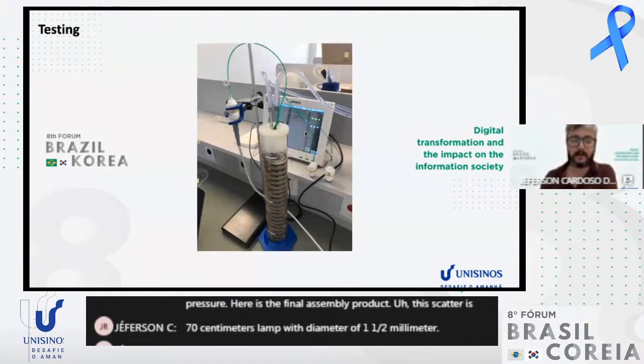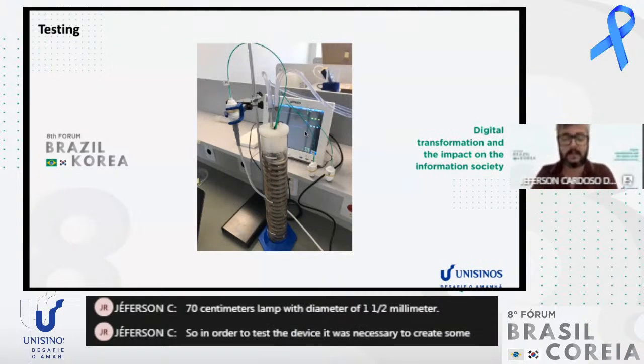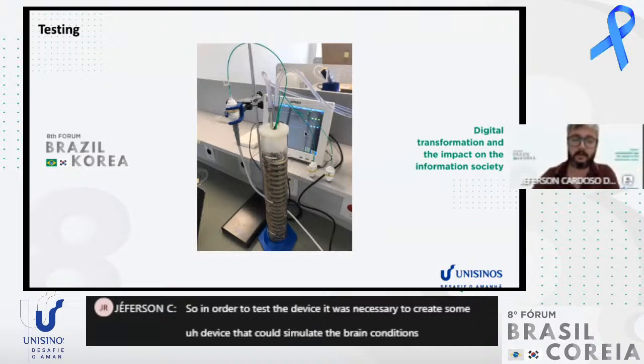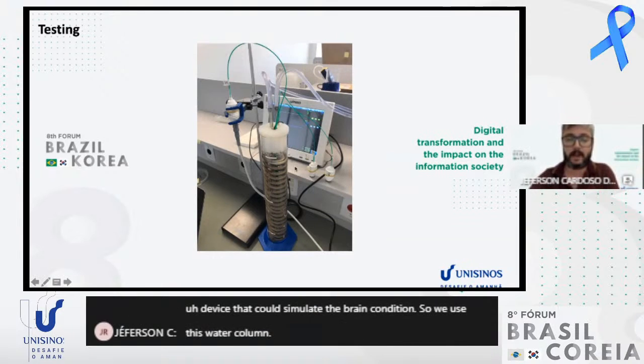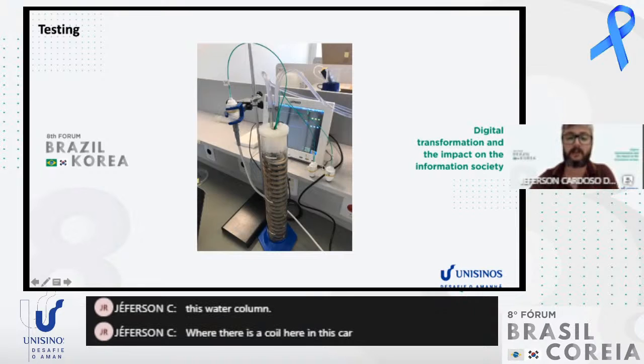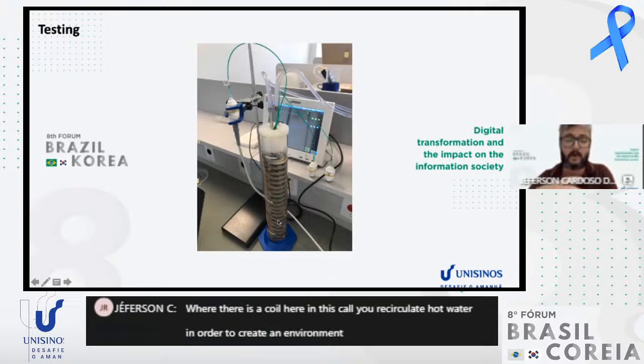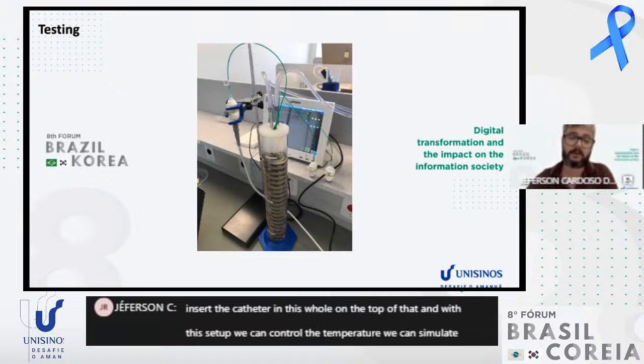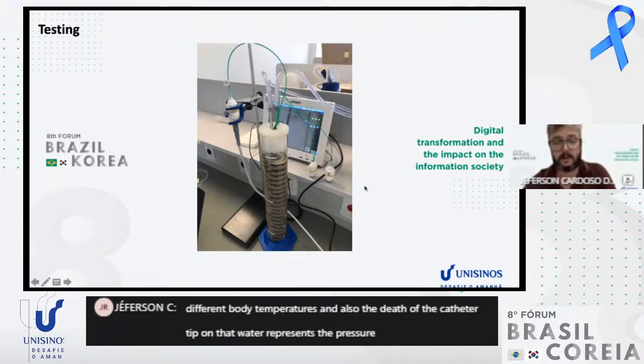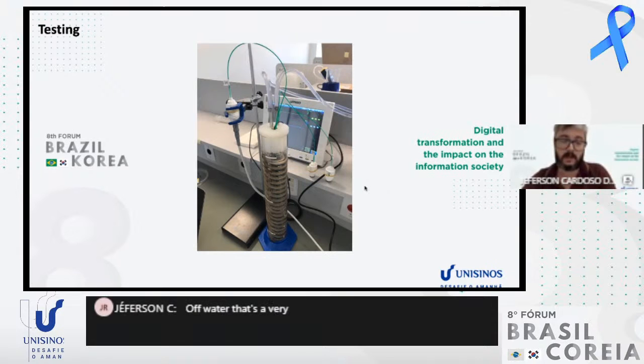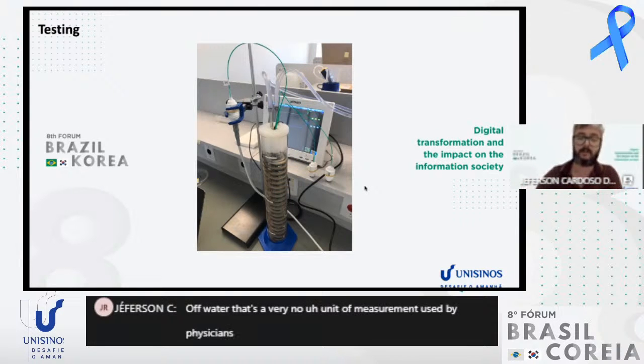So in order to test the device, it was necessary to create a device that could simulate the brain condition. So we use this water column where there is a coil here. In this coil, we circulate hot water in order to create an environment with very constant temperature along the column, and we insert the catheter in this hole on the top. With this setup, we can control the temperature. We can simulate different body temperatures. And also, the depth of the catheter tip in the water represents the pressure in centimeters of water. That's a very well-known unit of measurement used by physicians in the ICU.